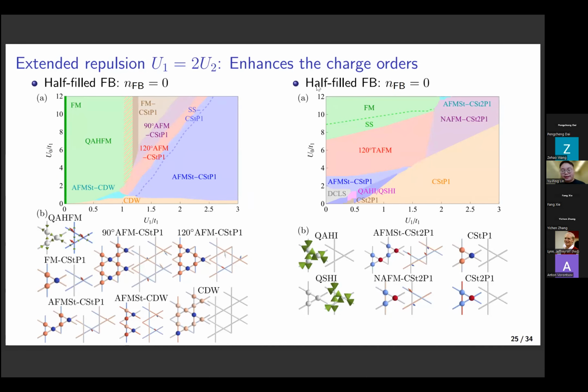And if we now look at the half-filled flatband, so this is the half-filling, which is n_FB equals 0, we will see that there is a very important occupation of the 120-degree coplanar order. In addition to that, we can also see the charge density wave, which is here, and also some other type of the antiferromagnetic stripe order. And also we can see a very narrow regime of the quantum anomalous insulator where you have loop current, or the quantum spin Hall insulator where you have the spin current. Okay, so this is what we found when we add the extended repulsion.